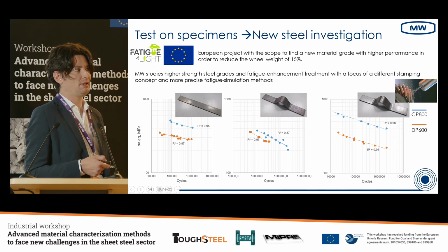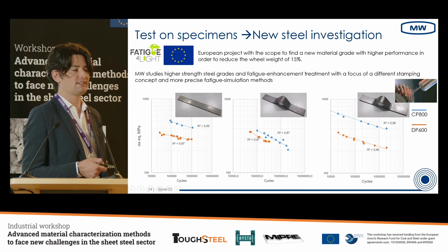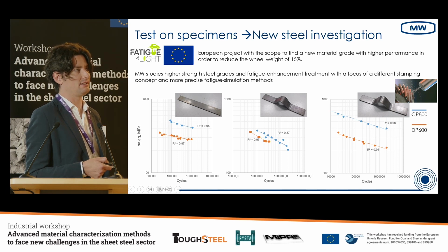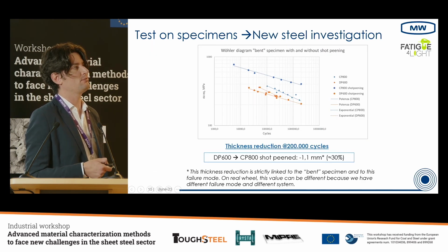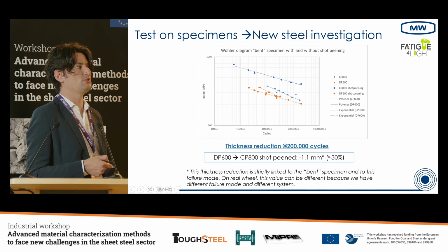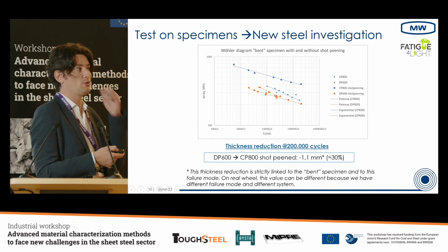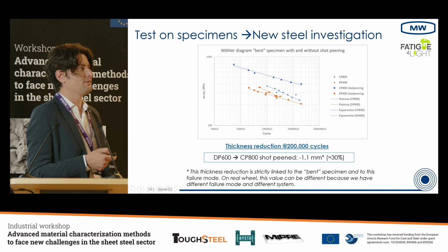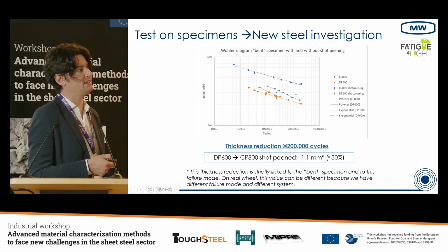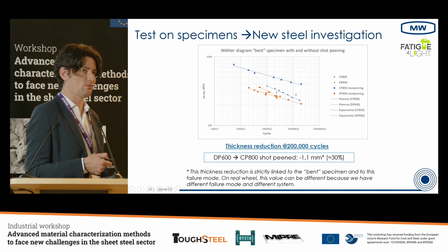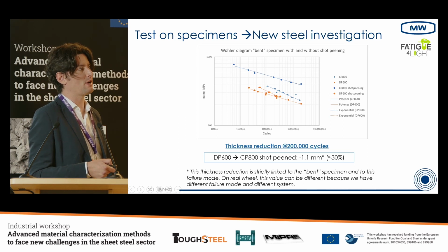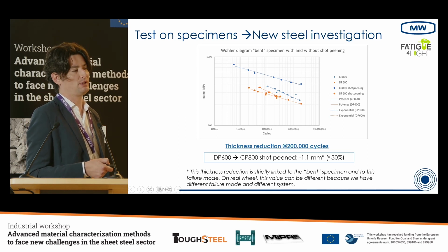But if we do the shot peening after the bending, again the CP800 improves a lot, and it is really better than the DP600. Here we have just a superimposition between DP600 and CP800 before and after the shot peening. You can see in orange we have the DP600. There is not much difference between before and after shot peening, but there is a huge difference on the CP800 after the shot peening. And so this can permit to reduce the thickness of the wheel a lot. For sure, in the bent specimen we have just one failure mode. In the wheel, we have more failure modes, so this 1.1 millimeter is not exactly what we have in the wheel, but we can reduce a lot.